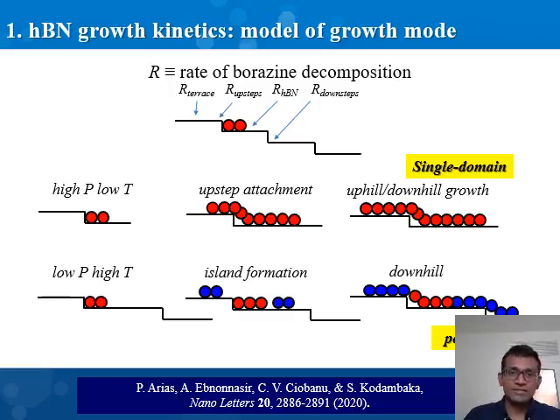And if we change the deposition conditions to lower pressures and higher temperatures, we think that the deposition starts at the down steps, but there are additional islands or domains forming on the terraces, which compete with the growth of domains attached at the steps. And I have intentionally colored these differently to indicate that these may be of different domain orientations. And eventually all these domains coalesce, leading to a carpet-like growth. However, the carpet growth mode is different from what is observed here. And under these conditions, one would expect to obtain a polydomain hexagonal boron nitride, in contrast to these deposition conditions where one obtains a single domain layer.